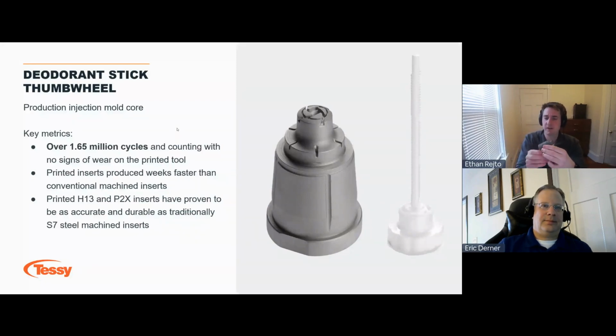And what they wanted to evaluate was, how does Mantle's H13 and how does Mantle's P2X or P20 material compare to a traditional tool steel? So they opened up the mold, they took out 3 inserts, they printed one with Mantle's H13, they printed one with Mantle's P2X, and they had one freshly machined out of S7 tool steel. Happy to say that this tool has been running for over a year now, over 1.65 million cycles and counting. It's probably even higher than that because it's opening and closing as I speak, and they've seen no signs of unexpected wear on the printed tool.